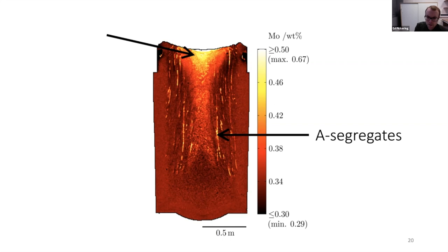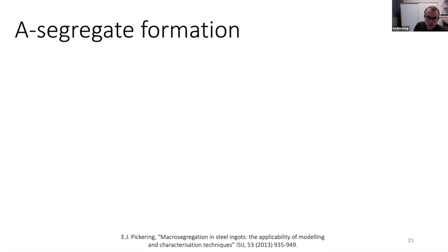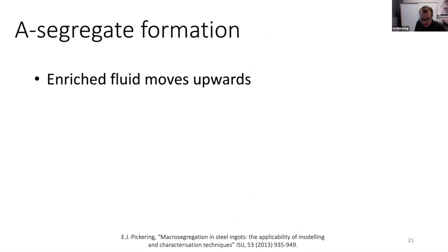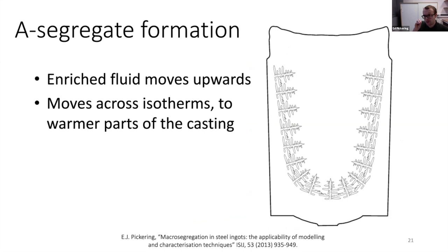And just to go into a little bit more detail about the A-segregate formation, when the enriched fluid moves, often it moves upwards, and in doing so, it crosses isotherms, basically, and it moves to warmer parts of the casting. So you introduce enriched liquid into warmer parts of the casting. And when you do this,